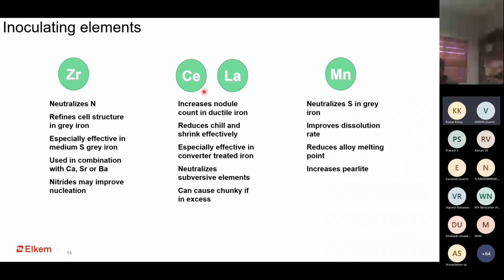The next one is zirconium. Zirconium-based inoculant, in combination with strontium, barium or calcium, and sometimes even independently, has a very balanced effect on casting solidification. It can find application in both grey and ductile iron castings. It does refine the structure in a very good manner, especially for castings which have heavy cores and can potentially have nitrogen fissure defects also. Zirconium inoculants find use there because they control the nitrogen fissure defect in the castings.